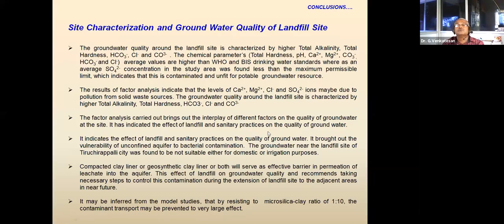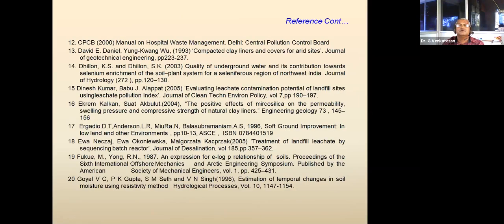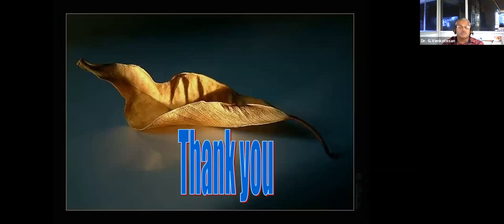Next, site characterization of groundwater quality at the landfill site. We found three groundwater samples and four bore wells were observed, and over a period of 1 year we obtained the results for anions and cations, compared with the WHO and BIS standards. It may be interpreted from the model studies that microsilica clay at 1:10 as a contaminant transfer barrier may have a large effect. We did it in clay soil as well as in the single clay liner system and the double clay liner system. These are your references. Thank you.